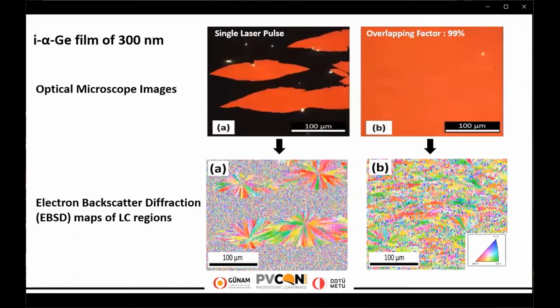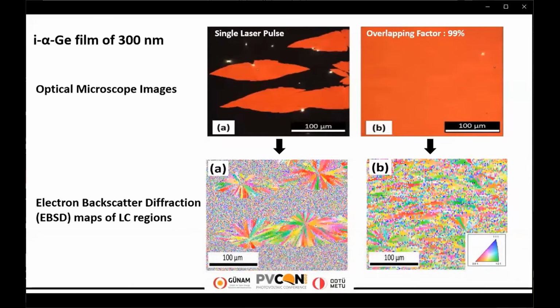And the scaled microscope image and corresponding electron backscatter diffraction maps of LC regions are seen. With a low laser fluence under laser crystallization condition, pinhole formation in the germanium film can be easily seen. Besides pinhole formation, the radial extension of germanium has been observed, which is centered around the defect during melting and crystallization of amorphous germanium. This indicates the explosive crystallization phenomena.